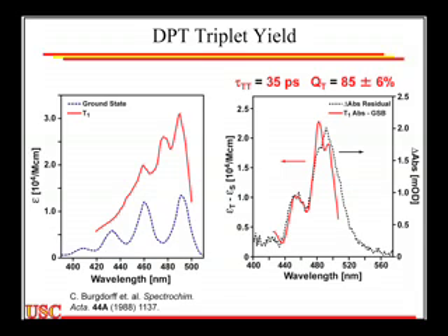I can measure the spectrum by simple subtraction. So I can go back to here, and even at early times, I can subtract out the triplet spectrum for the metal porphyrin compound. I can correct for that, and sure enough, this is the triplet absorption spectrum for DPT. We're very fortunate that somebody long time ago, in the 80s, measured the triplet spectrum by triplet sensitization.